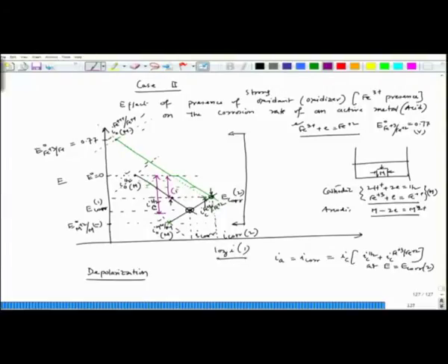So this is when Fe+3 is present, and this is without Fe+3. We could see that the overvoltage for the hydrogen evolution reaction has decreased due to the presence of Fe+3. That particular effect we call the depolarization effect on hydrogen evolution because of the presence of Fe+3. So Fe+3 is called a depolarizer.